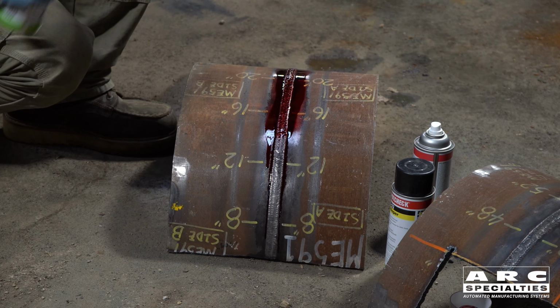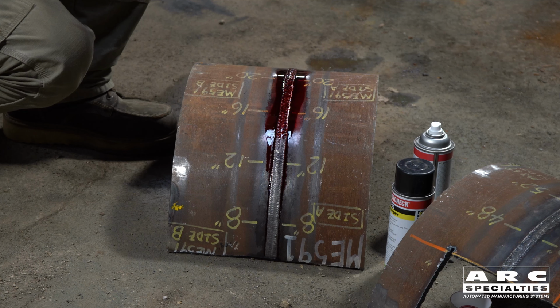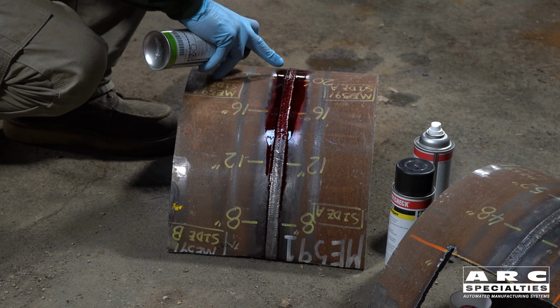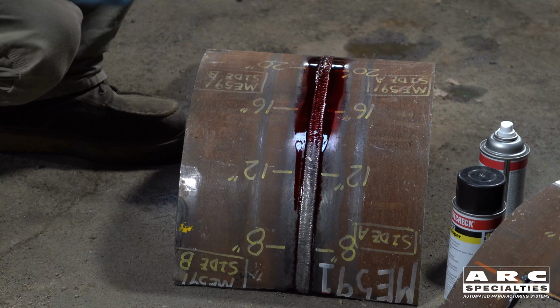And what are we looking for here? Cracks? We are looking for lack of fusion at the toe. We are looking for any linear indication that should not be in the surface of this weld area. So we have a dwell period of 10 minutes?